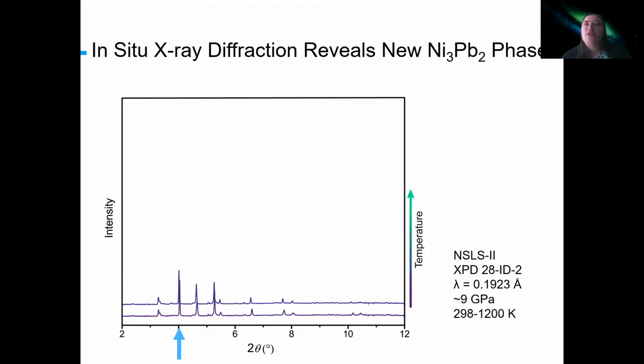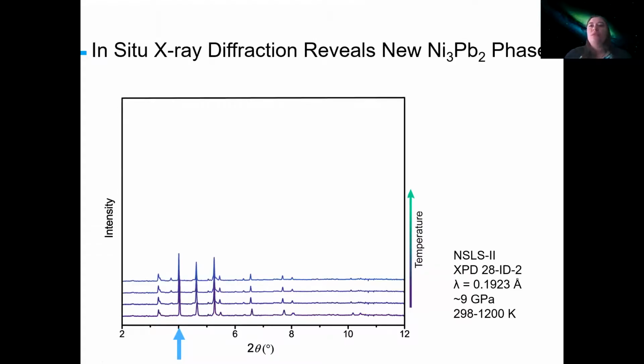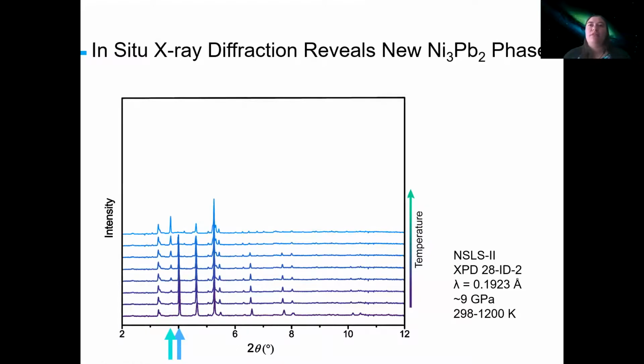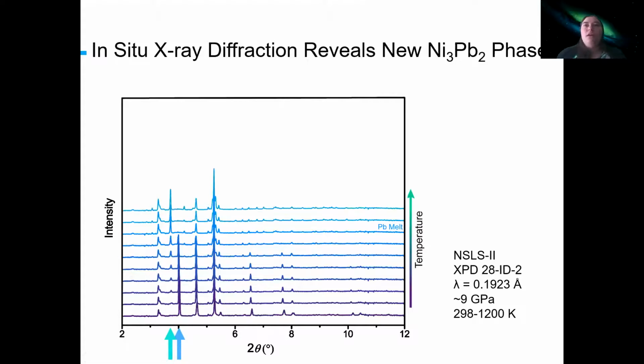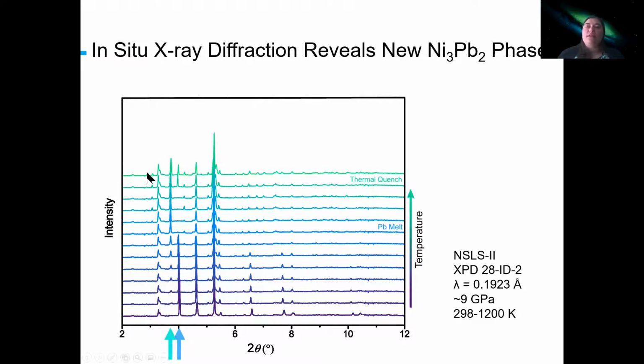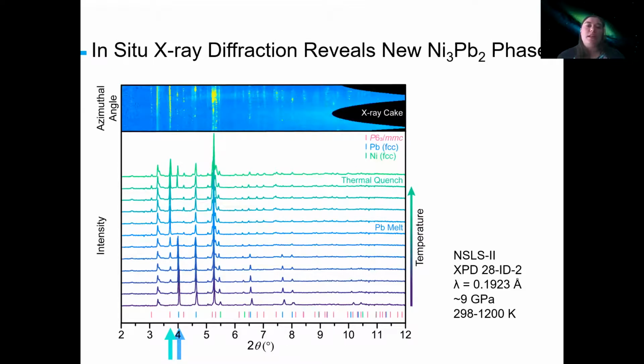And this is one of my absolute favorite days in lab, watching the formation of a new material for the first time. And what you'll notice here is the major lead peak that we're watching. You give it just a little bit of temperature and we start to see our new phase growing in. And that new phase really takes off once you get to the lead melt here. It continues to grow once you get past lead melt, and then upon thermal quenching, that phase sticks around. And the new phase we can index to a P63/mmc unit cell, which is consistent with what we see in the B8 structural family.